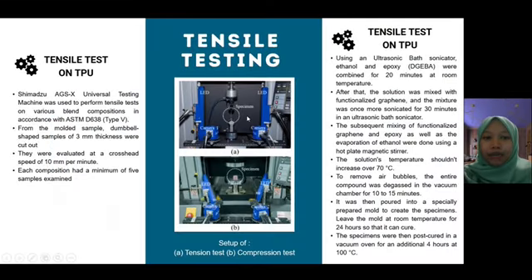So now, my name is NURUL RAHIM and I will present the part on the tensile test on TPU for our presentation today. Shimadzu AGSX Universal Testing Machine was used to perform tensile tests on various blend compositions in accordance with ASTM D638 Type 5. From the molded sample, dumbbell-shaped samples of 3 mm thickness were cut out, and they were evaluated at a crosshead speed of 10 mm per minute. Each composition had a minimum of 5 samples examined.